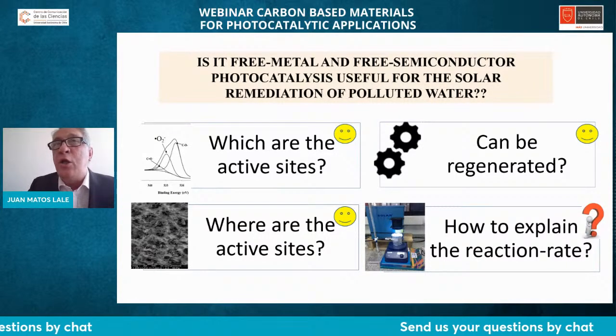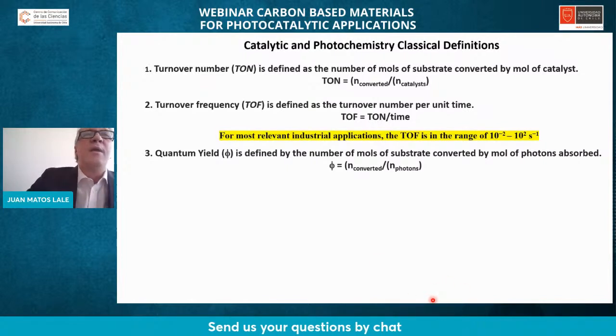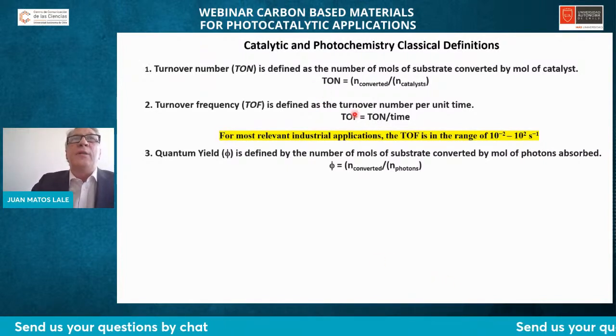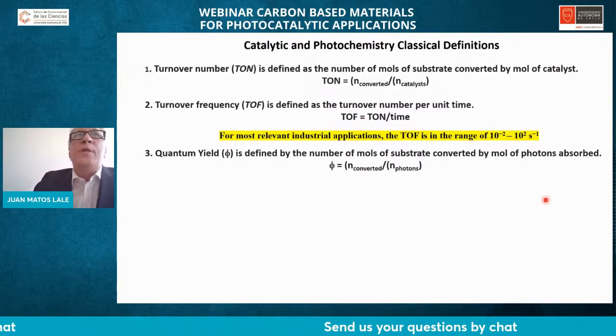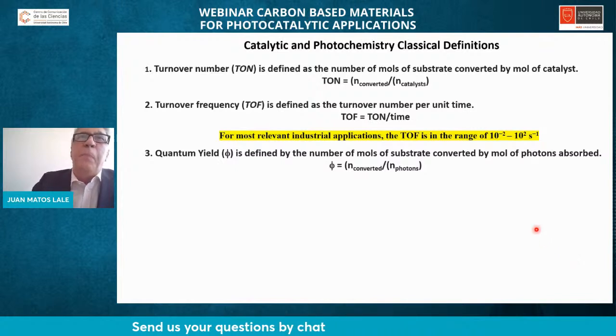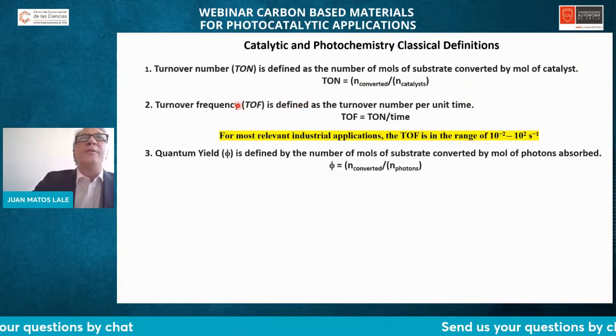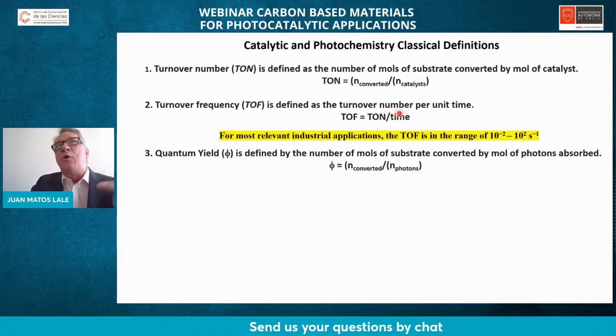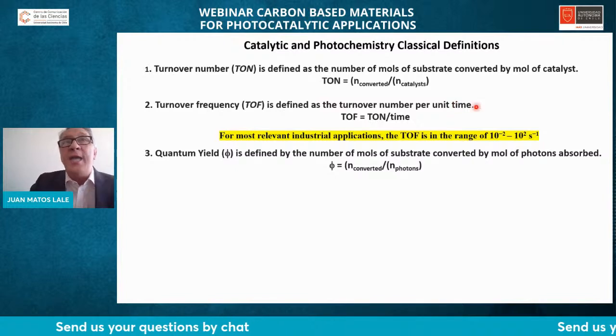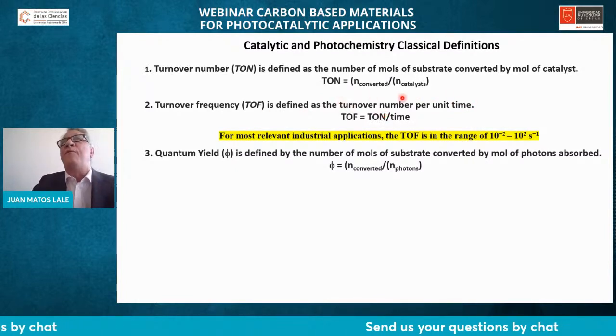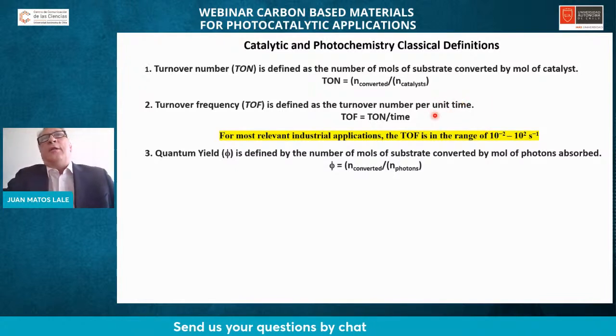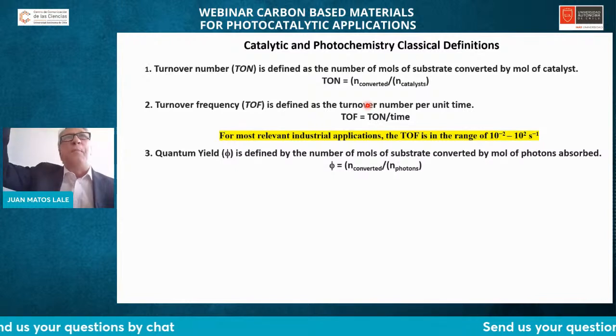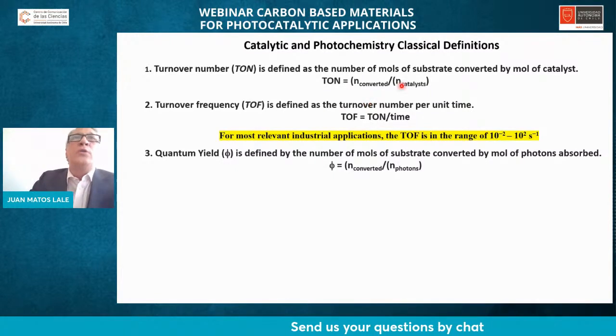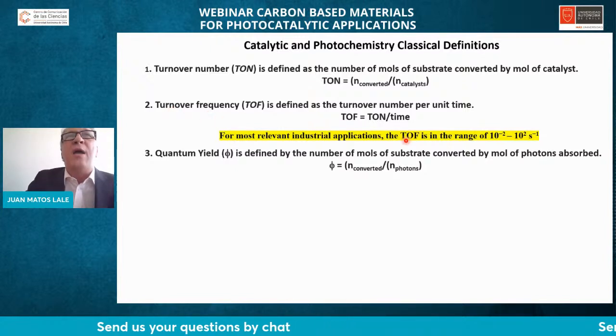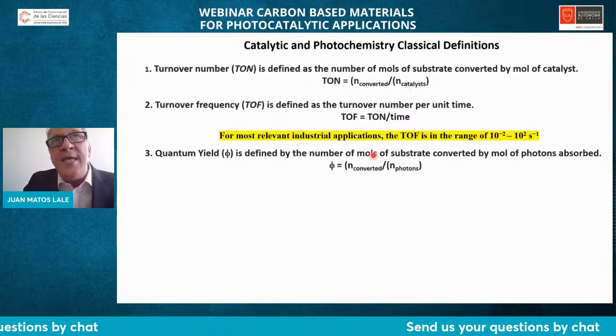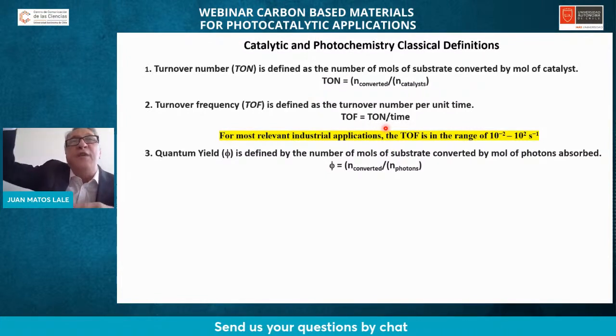The problem is how to explain correctly the reaction rate. It's not possible to explain now with the classical TON or TOF definition. We cannot explain correctly the quantum yield of the carbon-based porous material. The reason is because the TON, or the turnover number, is defined by the moles converted of reagent against the quantity of catalyst, all right? Is the number of moles of substrate converted by mole of catalyst. Alternatively, you can talk about moles of a specific product forming in steady state conditions against the moles of catalyst. At the same time, turnover frequency is defined by the TON against the time at the point that the product achieved the steady state condition.